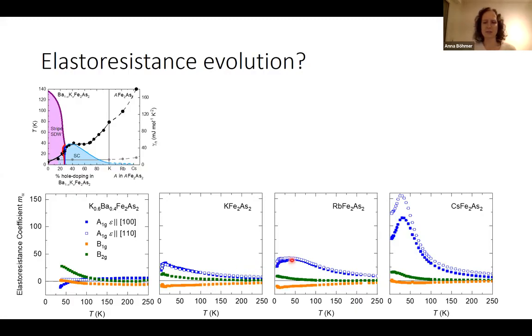We go further, and we see this growth of the A1G component, the in-plane symmetric one. The B2G one, that would be our nematic susceptibility, doesn't change very much anymore. It's there. And the B1G is finite as well, but does not diverge. There's no Curie-Weiss or power law dependence here. So the A1G component compares very well to our Grüneisen ratios, or even in temperature dependence, the thermal expansivity here. And there's a fundamental reason for that. It is that the resistance in these compounds is strongly dominated by the entropy. And so with the elastic resistance, the A1G coefficient, we actually get a measure of the Grüneisen ratio here.